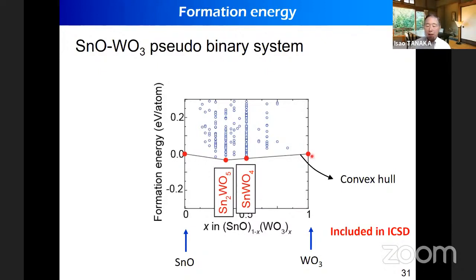And we have examined ICSD and found that in ICSD, there are 2 compounds reported, which correspond to these 2 compounds. So there is a good one-to-one correspondence between ICSD and our theoretical result. This is good news, but at the same time, we didn't find anything new. But this is a story of tungsten oxide.